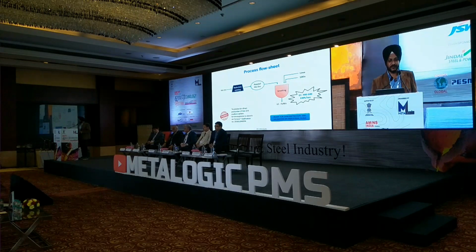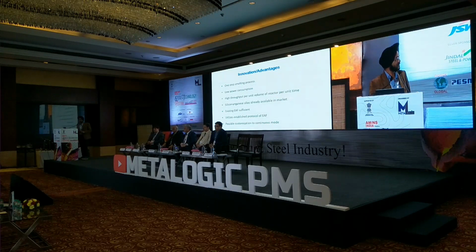This process is applied for patent, and this process is ready for demonstration, and the energy consumption is only 500 kilowatt hour per ton, whereas the conventional process for silicothermic reduction of manganese ore consumes around 2000 kilowatt hour per ton of energy. So there is definitely energy saving in application of this furnace.